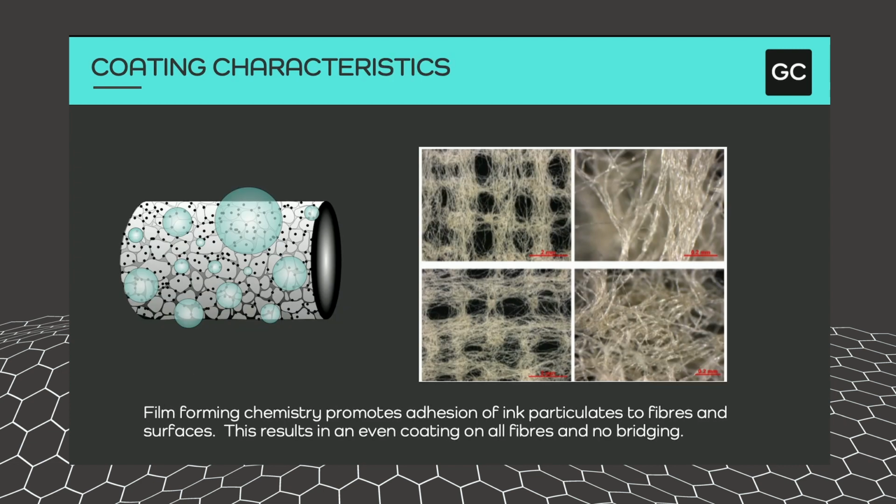The engineered coating adheres extremely well to cellulosic-based fibers. The 4 micrographs to the right show a cotton-based material coated with GC Halo ink. The ink imparts a slight brown coloration to the product, but there are no GO agglomerates to be seen, and the engineered film, which coats the entire fiber, increases the fiber width marginally, which results in a minimal impact on the pressure drop. The other graphic shows a representation of the silver decorated GO forming a continuous film on a fiber with water droplets to scale to show how the mechanism of attract, absorb and destroy works within the system.